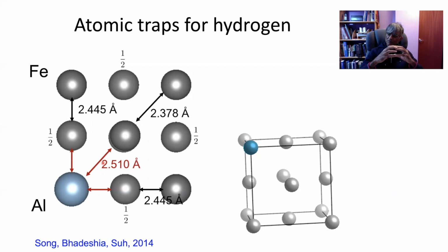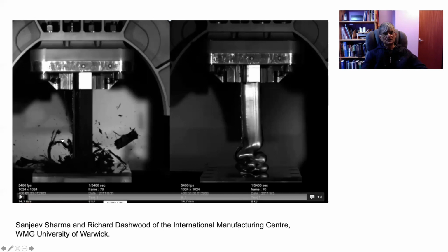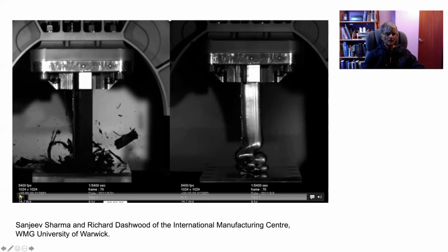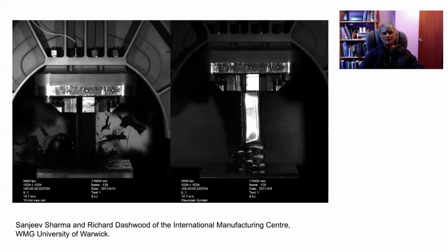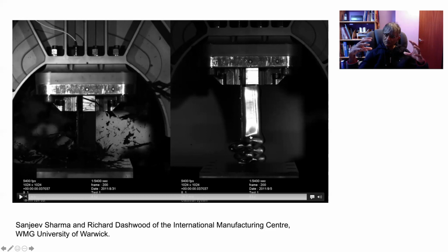Okay, so I'm going to show you a movie of this square-shaped object being rapidly deformed to test for its ability to absorb energy. On this side we have a steel component, and this side is a composite which absorbs energy by a different mechanism, by delaminating effectively. So here you go. This is at about 14, 15 meters per second. This kind of behavior is engineered into the component. When it concertinas, it begins to absorb energy, and therefore there is a level of protection for the passenger compartment and the engine block and so forth.